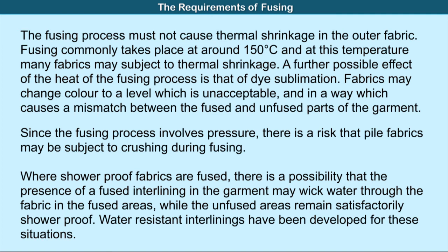Fusing commonly takes place at around 150 degrees centigrade, and at this temperature many fabrics may be subject to thermal shrinkage. A further possible effect of the heat of the fusing process is that of dye sublimation. Fabrics may change color to a level which is unacceptable, in a way which causes a mismatch between the fused and unfused parts of the garments.